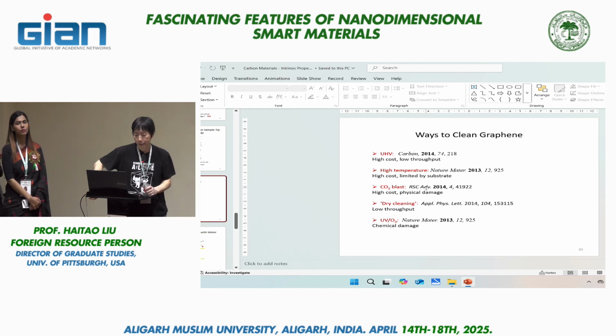The only other thing is high temperature annealing. You can do this at about 300, 400 degrees Celsius. You won't damage CVD graphene at that temperature, and you can apply reduced pressure at the same time. So depending on your requirement, but none of them will work perfectly. I'm a bit more pessimistic on that side, but on the other hand, if you can figure out a way to clean them very well, that can be a very impactful discovery.